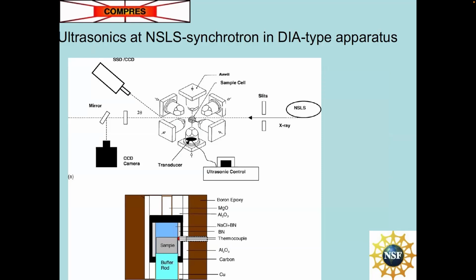So the next slide shows a schematic of what happens in this apparatus. So we've installed this DIA-type apparatus at NSLS. This is the blow up of the anvil assemblies, showing these 6 anvils compressing the cubic sample assembly. The acoustic wave can travel from the transducer through one of the buffer rods into and out of the specimen. So you have an ultrasonic signal. At the same time, in another direction, you have an X-ray signal coming in from this side, beg your pardon. This is the X-ray diffracted along the 2 theta line into a solid state detector.